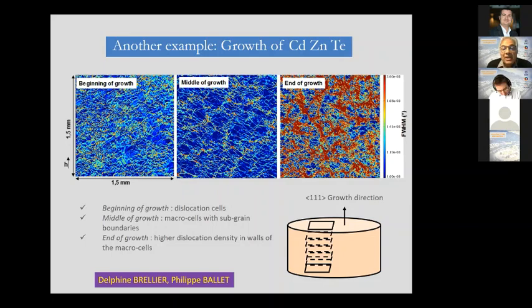Another example is the growth of a cadmium zinc telluride. And the people who grew this crystal wished to know if the crystal was as good as or worse than the one that you can commercially buy. And actually the result was that along the growth direction, they had everything: better in the middle, same as the commercially produced at the beginning of the growth, and worse at the end of the growth. So you can characterize by using these full width half maximum maps in a very easy way the quality of your crystals.